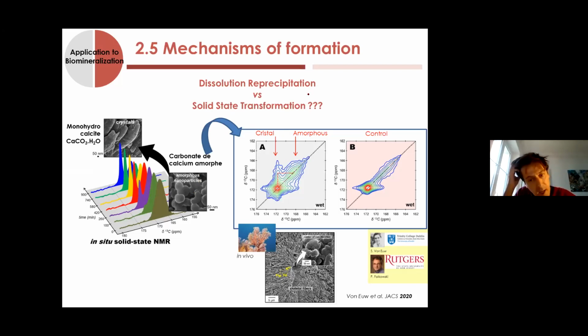There was a long debate about the mechanism of transformation when you go from an amorphous phase to the crystalline phase, especially in vivo, because in vivo it's a wet environment. You are surrounded by water molecules, and most of the time people were saying, okay, in that case you have some mechanism of dissolution and then reprecipitation of the crystal phase.